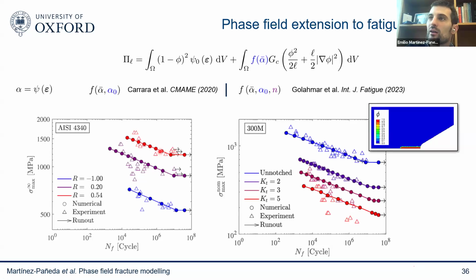So you can see, for example, here, that once we know the value of these two material parameters for this particular material that we're interested in, we can then simulate fracture experiment or fatigue experiment, these are SN curves, at different load ratios. And you can see that we can naturally go from one to the other. So you need one experiment of your relevant material, and then we can predict what's going to happen in the lab, but also in engineering practice and the different loading conditions. So I think that is quite powerful.